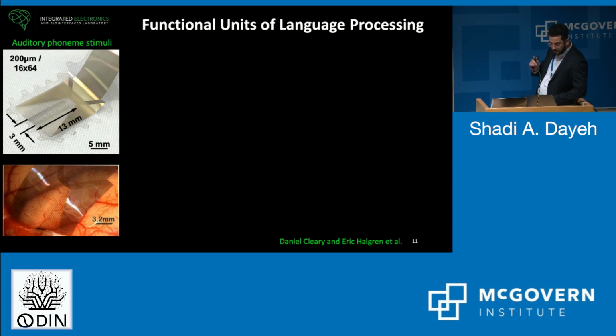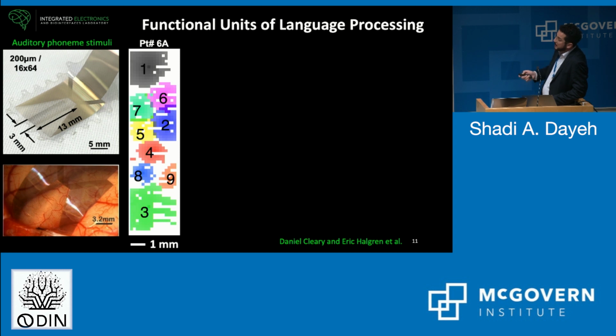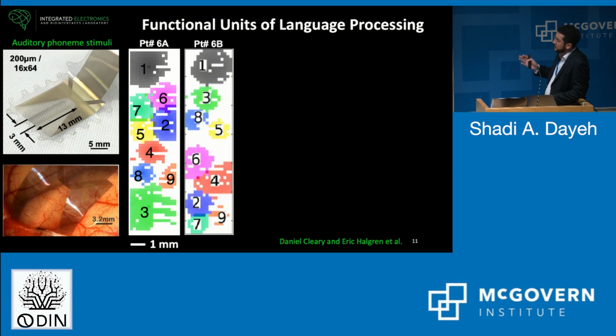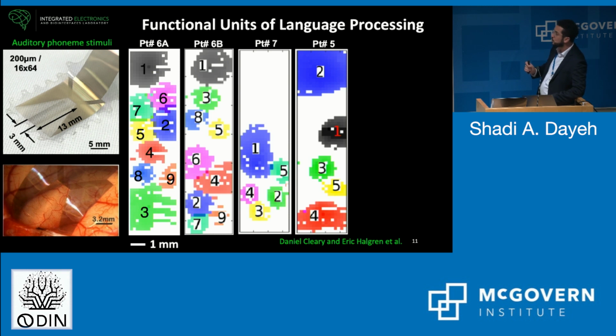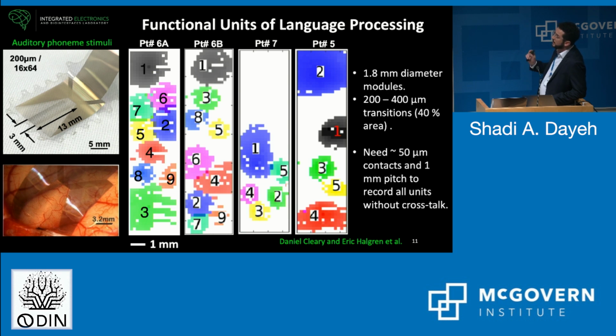Now, in another configuration where patients are listening to auditory stimuli, we placed a high-resolution grid with 200 micron pitch on the superior temporal gyrus, and we have a randomized trial from Eric Hallgren's lab where different phonemes and noise are induced, and across these trials, across different patients, we observed responsive regions or modules. These are cortical domains or functional units that are associated with each individual English phoneme. Now, the diameter of these modules is on average about 1.8 millimeters, with a transition of about 0.4 millimeters between two adjacent domains. Therefore, if we want to resolve these domains with high gamma activity, as shown here, or with ripples, we'd need a resolution of at least 1 millimeter, with contacts that are at most about 100 micrometers in diameter or so.